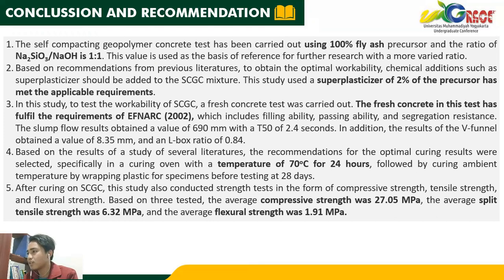The study used a superplasticizer of 2% of the precursor, which met the applicable requirement. And in this study, the workability test of fresh SCGC was carried out. The fresh concrete in the test has fulfilled the requirement of EFNARC 2002, which includes filling ability, passing ability, and segregation resistance. Based on the results of several literature studies, the recommendation for optimal curing was selected, especially curing in an oven at a temperature of 70 degrees Celsius for 24 hours, followed by curing at ambient temperature by wrapping the specimens in plastic before testing at 28 days.